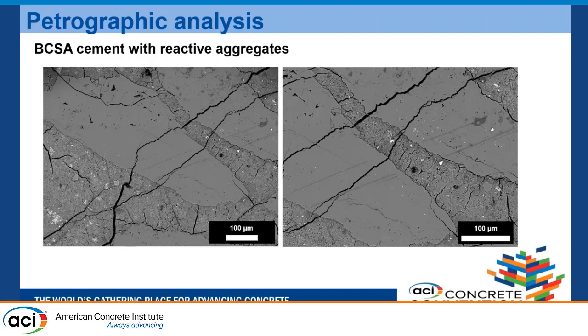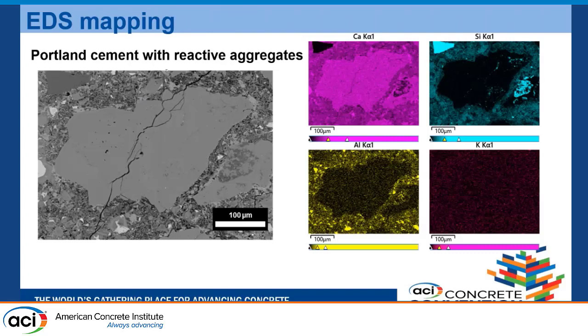Even though it cracks, BCSA cement again shows ASR cracks. But based on the comparison with the long-term test, even though it cracks, the expansion is not too high compared to the performance of Portland cement with reactive aggregates. So I'll be doing further analysis.